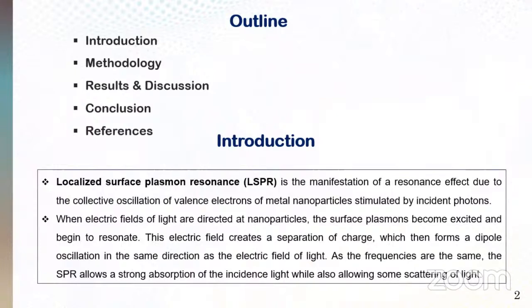Manifestation of a resonance effect due to the collective oscillation of valence electrons of metal nanoparticles stimulated by incident photons is known as localized surface plasmon resonance, or LSPR effect. When electric fields of light are directed at nanoparticles, the surface plasmons become excited and begin to resonate. This electric field creates a separation of charge, which then forms a dipole oscillation in the same direction as the electric field of light. As the frequencies are the same, the SPR allows a strong absorption of the incident light, while also allowing some scattering of light. This study focuses on how to utilize this LSPR effect of gold nanoparticles in efficiency enhancement of quantum dot sensitized solar cells, QDSSCs.